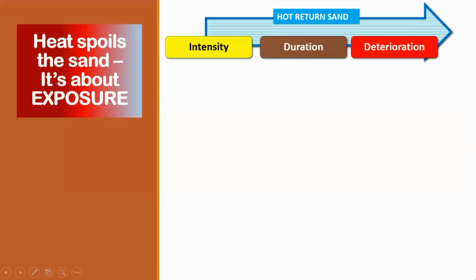So now we'll talk about the heat and its exposure. The return sand, which is hot. How much it will get affected is based on the intensity of the heat that is given to the sand and how long it is getting affected and how much it is going to get deteriorated over a period of time. This is all before it gets cooled. So that means everything is happening when it is hot. So obviously, if you can reduce the time duration for this exposure to heat, the sand is going to remain much better than leaving it hot overnight or not bothering to cool it at all.